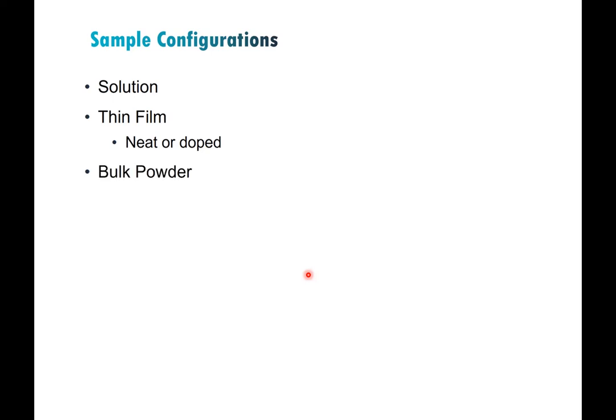You can also do measurements on bulk powders, which is more common in the solid-state world. Something a little more rare is doing photoluminescence on single crystals. There are potential advantages, particularly if you have a goniometer that can align the crystal, because these excited state transitions are often polarized in one or more directions, not necessarily isotropic. By doing it on a single crystal you can get information about the polarization of the state, which can tell you what type of excited state it is. Single crystal measurements are pretty cool but just not very common or easy to do.